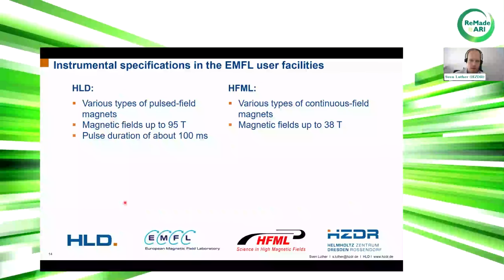Now I want to give you some instrumental specifications in both our EMFL labs. So at the HLD, we are running various types of pulse field magnets, which can create magnetic fields up to a maximum of 95 Tesla, with a pulse duration usually of about 100 milliseconds. In the HFML, we have various types of continuous field magnets, which can create magnetic fields up to 38 Tesla.